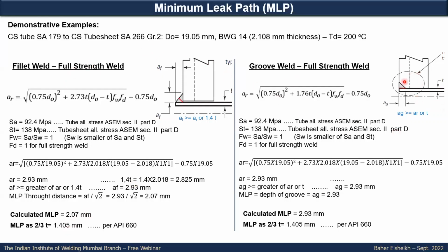For the same example, we calculated for the only groove, and for the groove, the same equation of the a_r here, but here the a_g should be the minimum of t or the a_r. So in this case, it will be 2.93, same. And the calculated minimum leak path will be 2.93 because this will be the side of the weld joint of the groove. So it is the same like the a_g. While we are calculating as per API 660, 1.405. So here also it is much more conservative compared to API, and also compared to the requirement for the fillet weld. This is one approach to think about the minimum leak path, which should be checked in the mock-up.